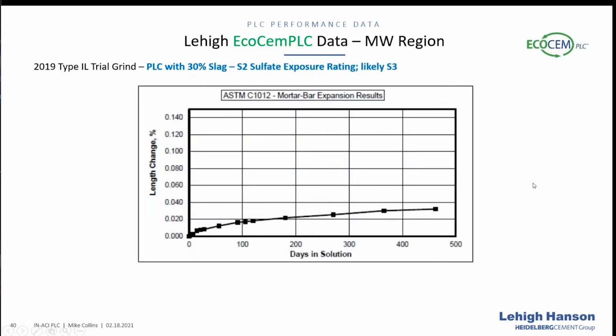When we put that in a mix with 30% slag, it really is starting to flatten out, and it's already met S2 sulfate exposure. I would expect that to easily reach S3 as well. We're going to carry that on out to the 18-month mark, but I don't expect it to do anything crazy and not make S3 at that point. From some early testing, what we're seeing is that the limestone cement has no adverse reactions to sulfate. It performs very typically compared to the C150 cement at the plant where it was produced. We've also sent all 4 PLCs from the Midwest region out for 1012 testing as well.